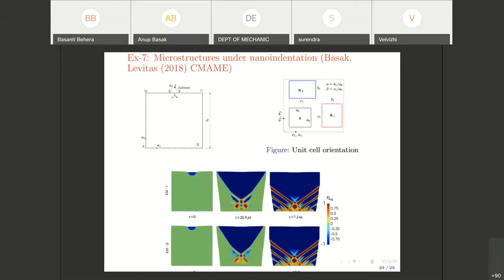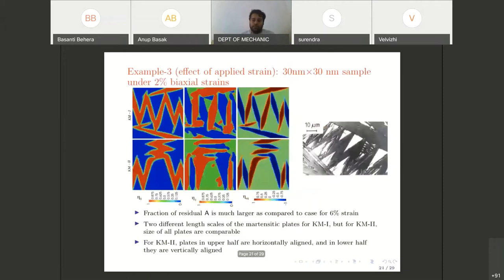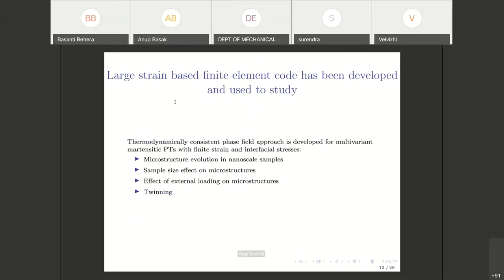A final example shows microstructure evolution under indentation loading: starting from austenite, martensitic variants evolve around the indentation zone with increasing displacement. This matches experimental observations of microstructure evolution under indentation in shape memory alloys. In conclusion, phase field models can efficiently predict martensitic microstructure evolution and the evolution of material properties under complex thermomechanical loading in shape memory alloys.